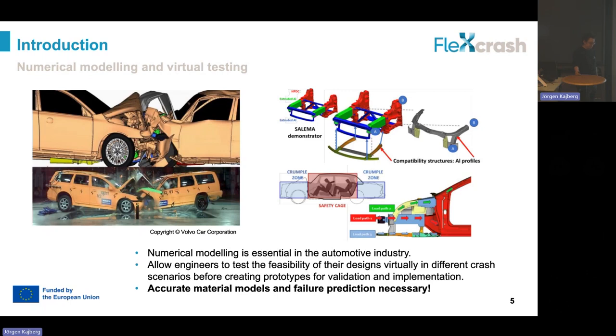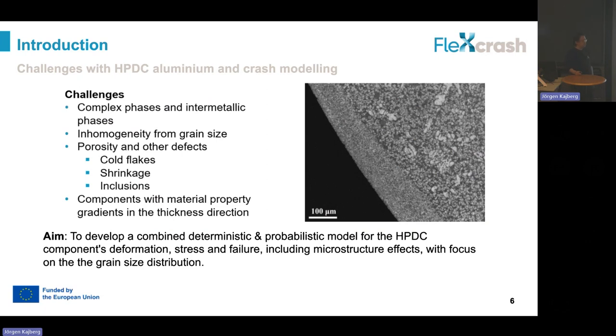And in this project, we use aluminium. And one of the techniques that we use is the high pressure die casting, where we cast our parts. And this introduces some challenges, because we have complex phases and intermetallic phase inhomogeneity. We have porosity such as cold flakes, shrinkage, inclusions. And we also have material property gradients in the thickness. So this is hard to model. So the aim that we have in this project is to develop a combined deterministic and probabilistic model for the high pressure die casting components' deformation, stress, and failure, including microstructure effects with focus on the grain size distribution.